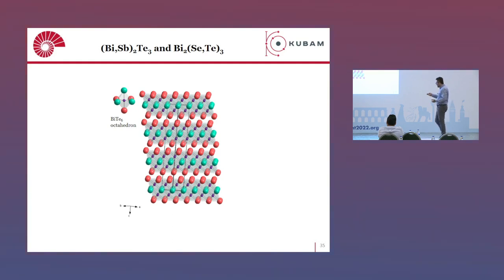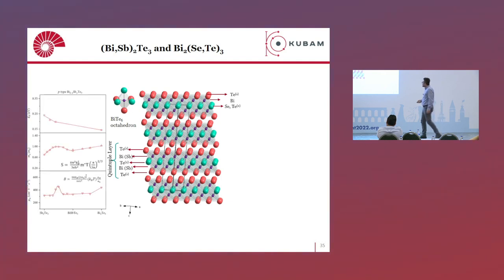So here is the unique crystal structure of this. We see in this crystal structure these layers of bismuth telluride, which are called quintuple layers. In the crystal structure, we have these bismuth atoms octahedrally coordinated with the selenium, with the tellurium. And if you do a solid solution of bismuth telluride with antimony telluride, you can also engineer the mobility, effective mass, and the band gap. We focused on these two materials.